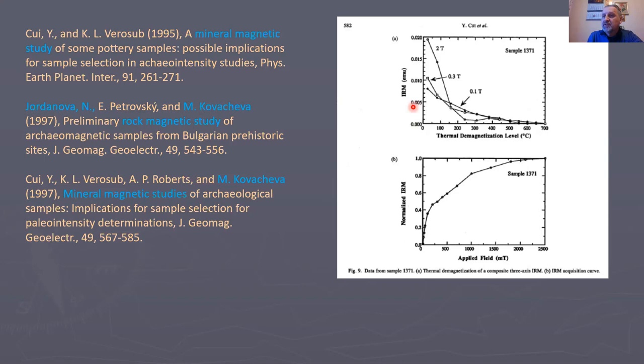In this figure, you can see one of the samples from the huge collection kept in Sofia. The three-axis Lowrie test shows a very tremendous drop of the hard, two Tesla component of magnetization below something like 240 degrees centigrade. And if we look at the IRM acquisition curve, we see that at least half of the magnetization is acquired above 300 millitesla.